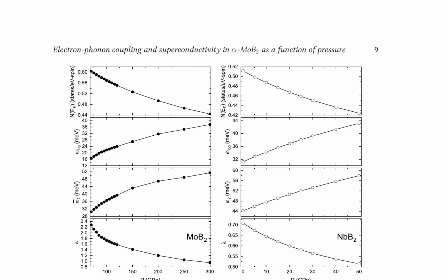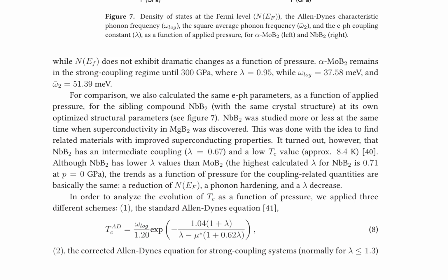Electron-phonon coupling and superconductivity in alpha MoB2 are investigated as a function of pressure. The density of states at the Fermi level, the Allen-Dynes characteristic phonon frequency, the square average phonon frequency, and the EPH coupling constant are all calculated. Alpha MoB2 remains in the strong coupling regime until 300 gigapascals, with lambda equals 0.95. These parameters are compared to those of NbB2, revealing differences in coupling strength and superconducting properties.